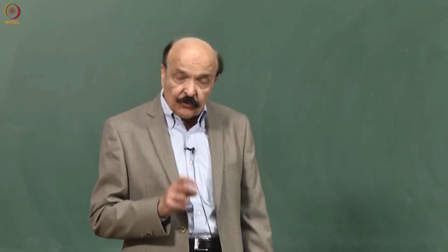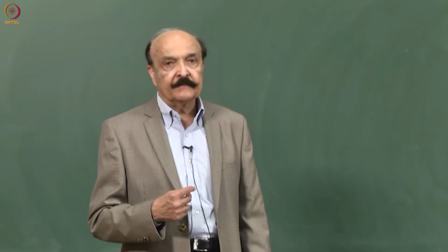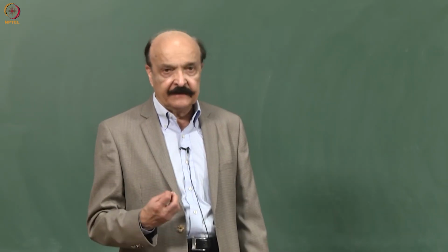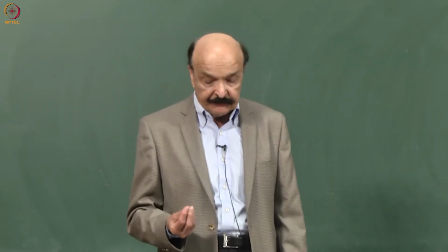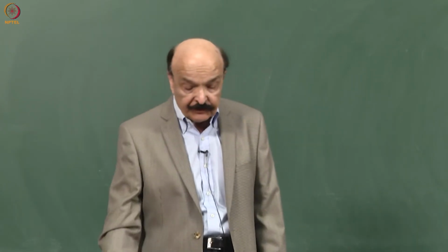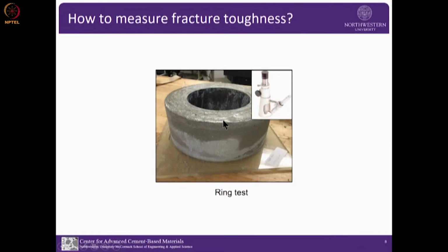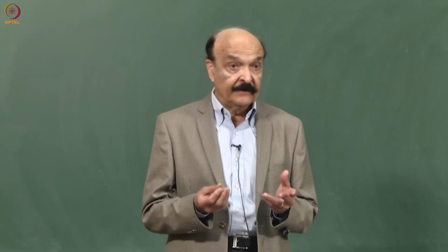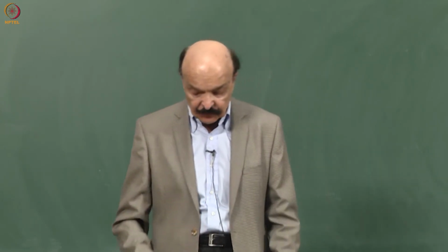And it's a good way to evaluate the crack potential of a material, and different types of fibers. For example, we showed that when you make a high strength concrete, and compare it with normal strength, high strength would have a higher tensile strength, but because it's more brittle, it cracks earlier than normal concrete. So this is a very good test.